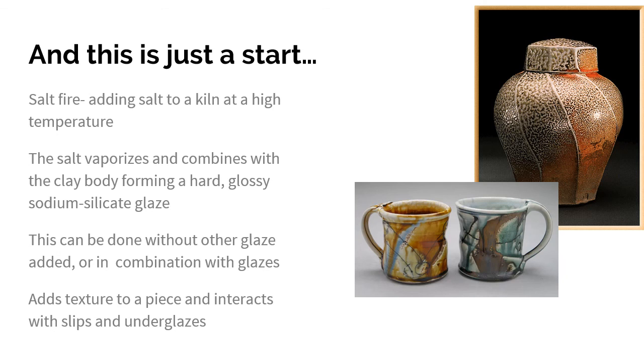And so salt kilns are really popular for adding some interesting texture, and also for working with glaze in a slightly different way. So the piece on top, you can see a lot of texture. The piece on bottom, a salt-fired kiln, playing with slips, and looking at that salt firing result. A lot of different things can happen with it. It usually gives you a more rustic quality in your final pieces.